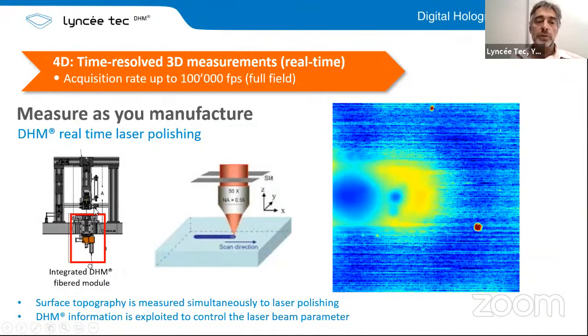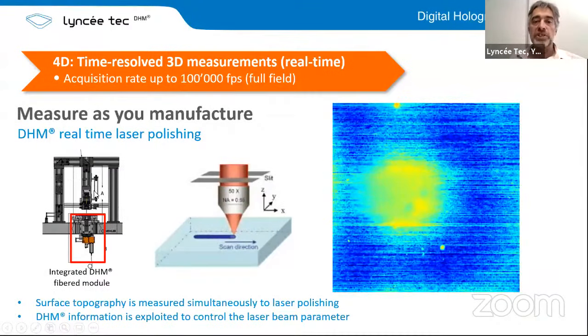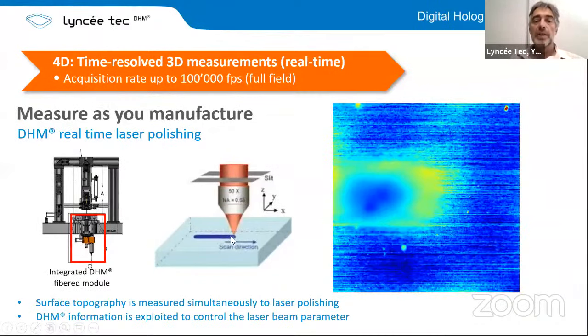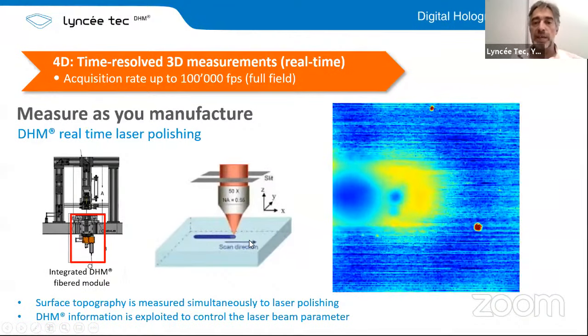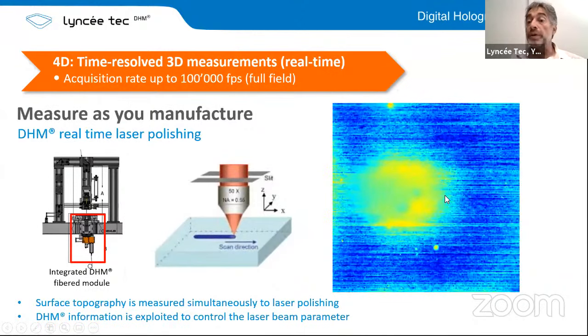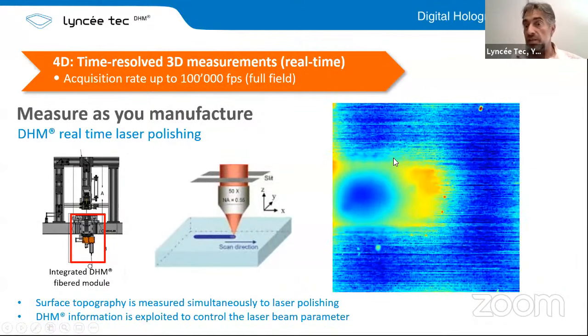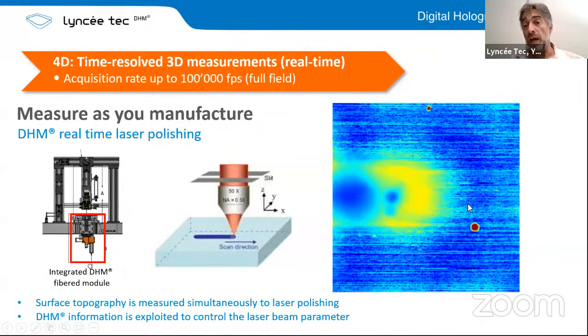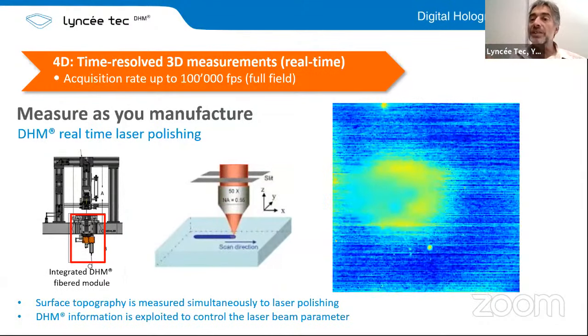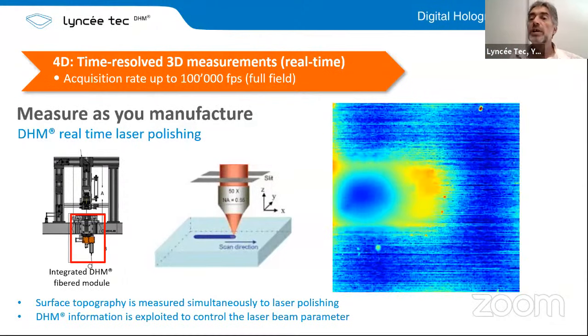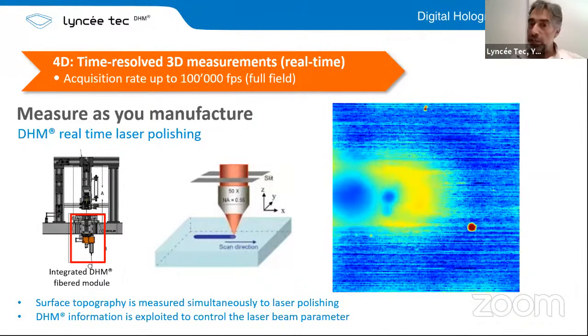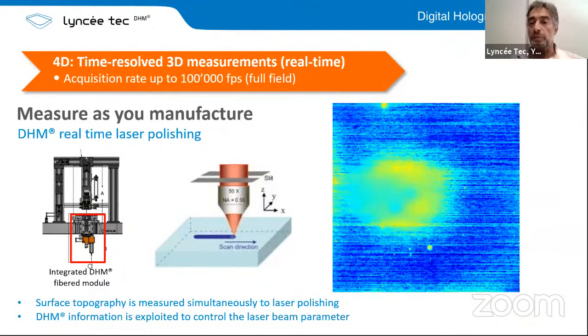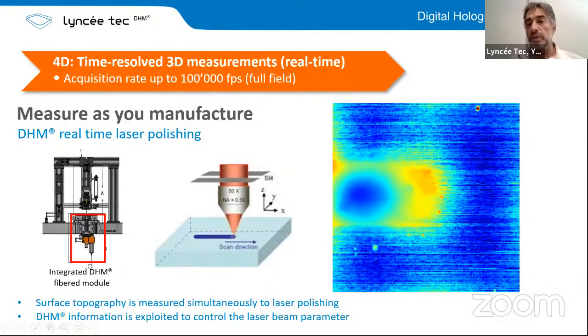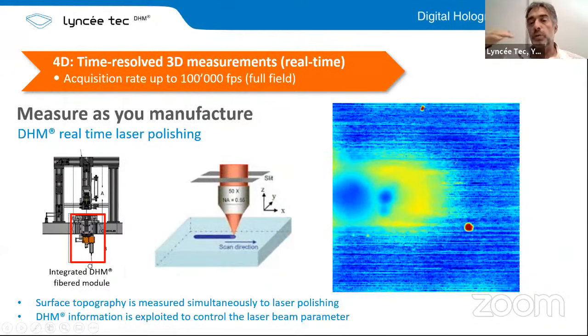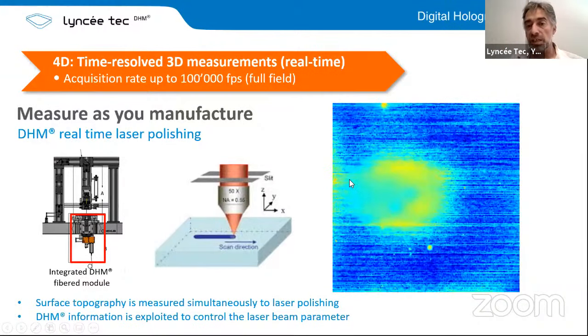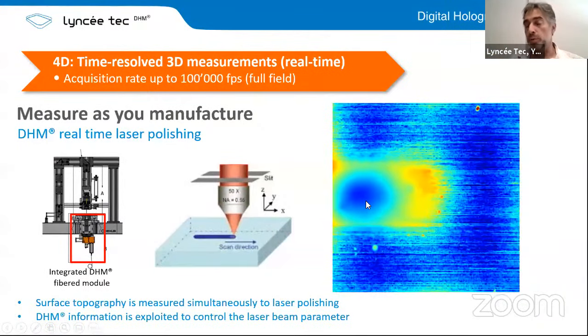So we have modules that we can integrate into other machines. This is a polishing laser. There is a continuous scan of the sample, and we measure during the polishing. And we can see here, this will be what you will see on the screen in real time. So it's possible immediately to get a feedback to the laser, so you can adjust the geometry of the beam or the power of the beam or whatever, and you can make sure that you are really polishing it, but you are not deforming the surface. You can see here there is some overheating, and you end up deforming it.